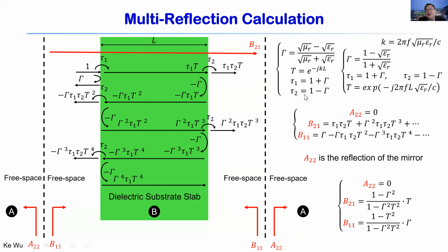We can use this technique to develop the very standard multi-reflection using linear superposition here, because all the reflection and transmission here are subject to linear superposition. So we can get the total transmission and reflection through this formula. This is a very standard formula. But for the B here, B only talks about these blocks here, while A talks about it here. Of course, A is in the free space air region. So we assume that there's a perfect match at the end of the measurements, so A1, A22 becomes 0, and so on. So the formula can be developed through these very simple equations.